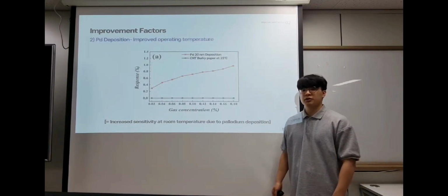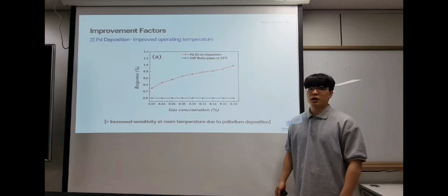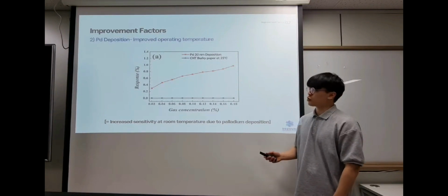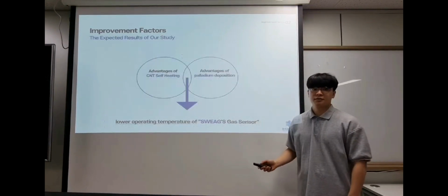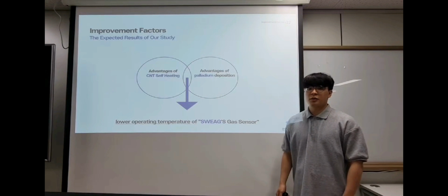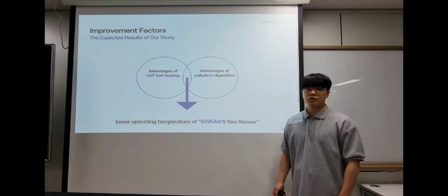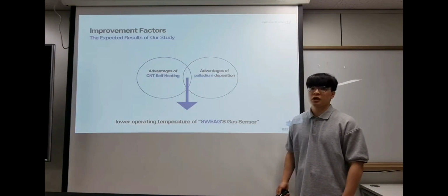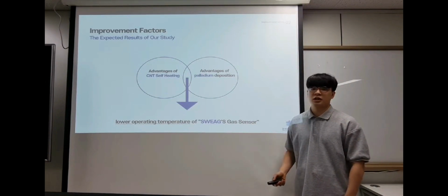In a similar experiment, when palladium was deposited on bucky paper of CNT by 20 nanometers, the sensitivity at room temperature increased. In conclusion, the expected result of our study is to develop sensors that detect hydrogen at lower operating temperatures through self-heating and palladium deposition to CNTs.